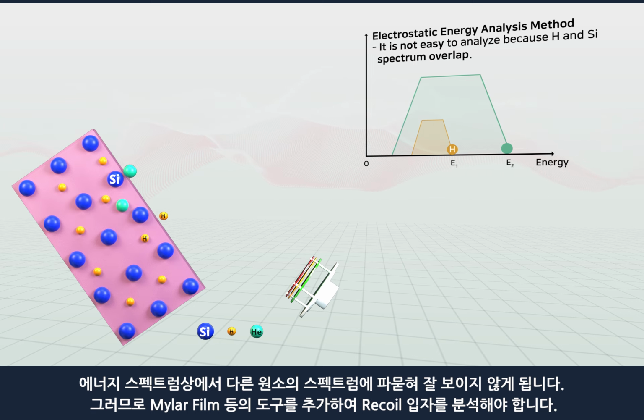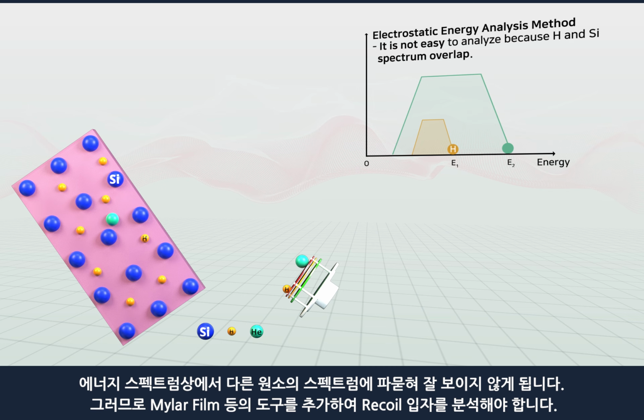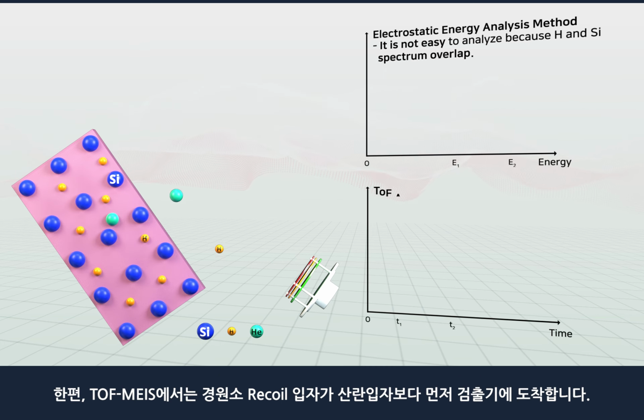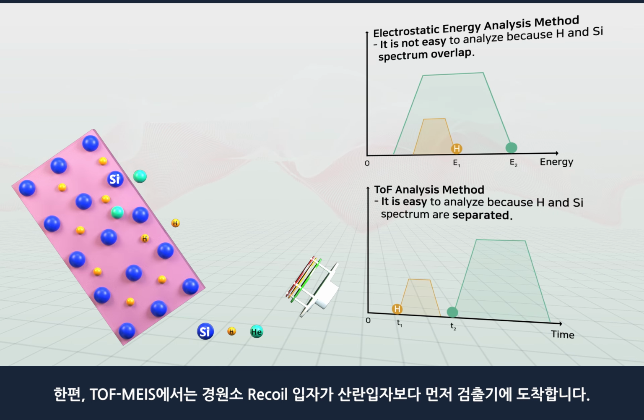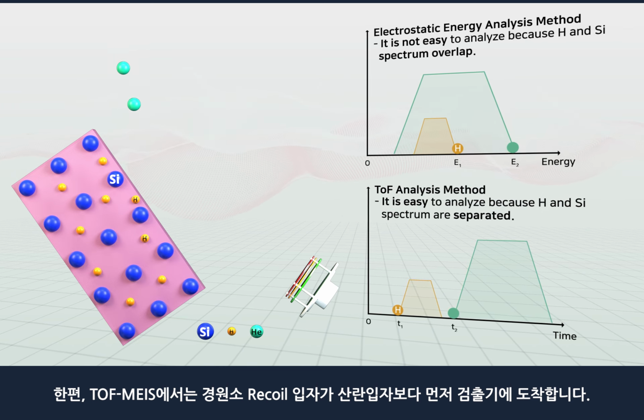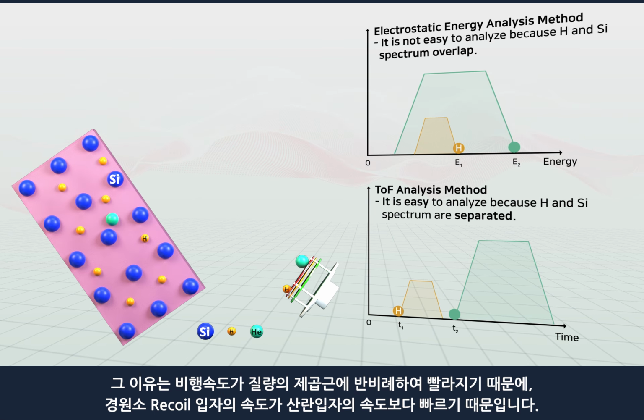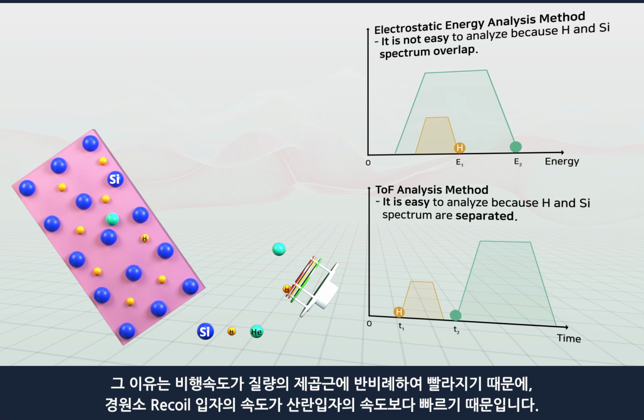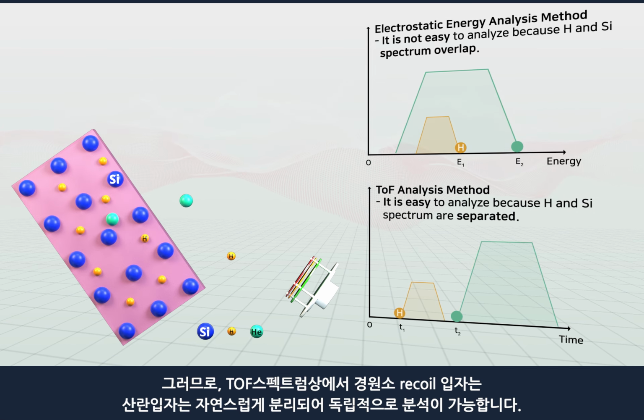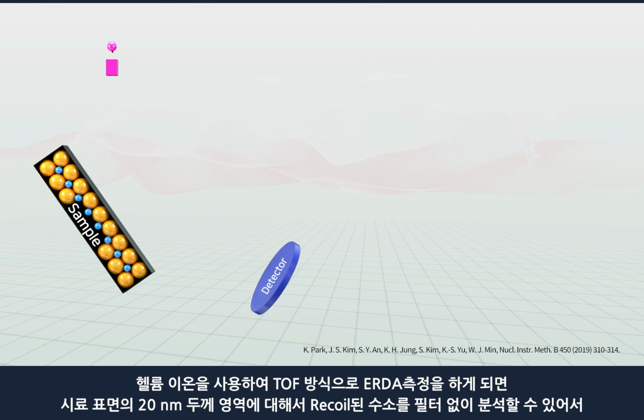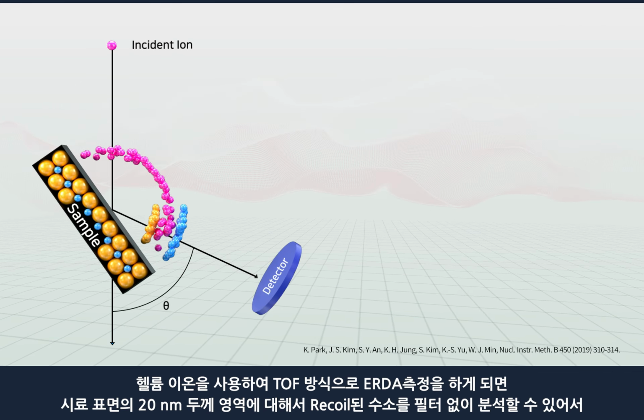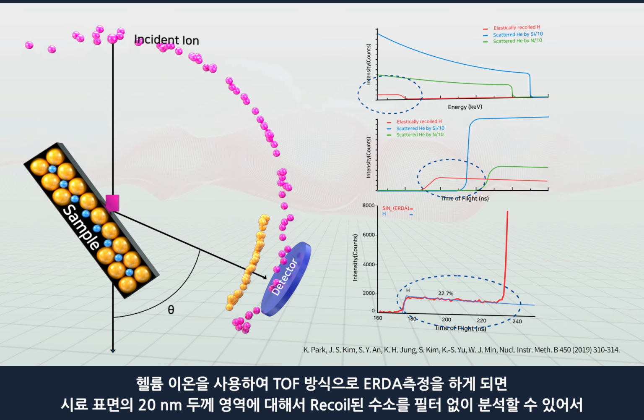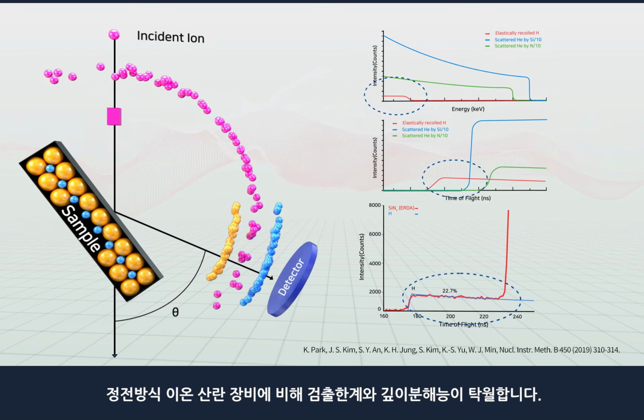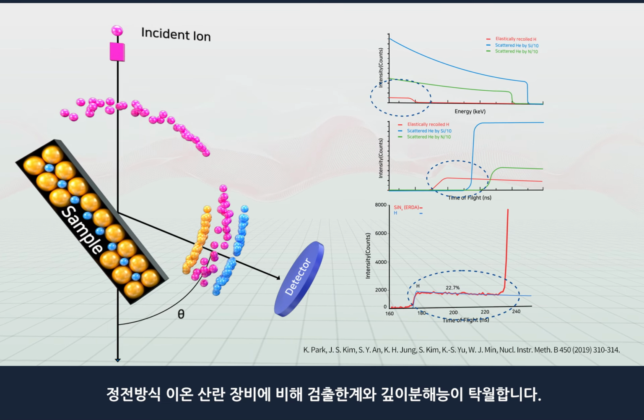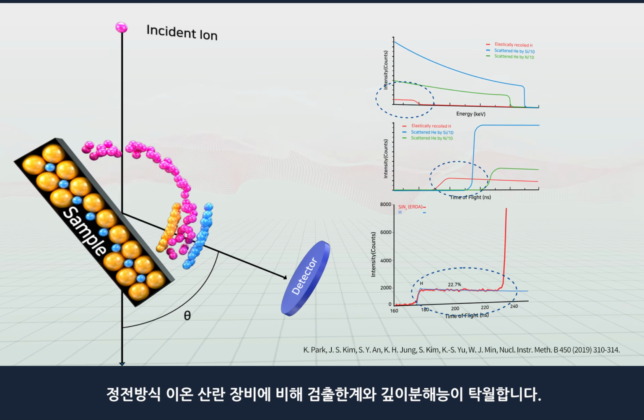Therefore, additional tools, such as a mylar film, should be added to analyze recoil particles. In comparison, a light element recoil particle reaches the detector earlier than a scattered particle in TOF-MEIS. This is because the flight speed increases in inverse proportion to the square root of mass. Therefore, the recoil spectrum is naturally separated from the scattered spectrum. If ERDA is measured by the TOF method using helium ions, recoiled hydrogen can be analyzed without a filter in the 20 nanometers thick region of the sample surface. Thus, this method has an excellent detection limit and depth resolution compared with other RBS type equipment.